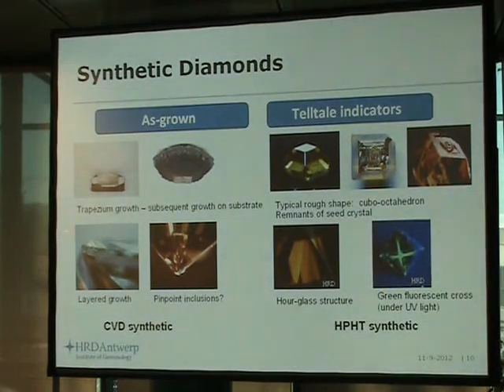Other indications that can point to CVD synthetic growth is that you could have some layered structure indications or pinpoints, but these only are indications. For conclusions, you have to go further. With respect to high pressure, high temperature synthetic diamonds, one can encounter remnants of the seed crystal, metallic inclusions, because the high pressure, high temperature synthesis method includes metal catalysts to facilitate the growth. Other indications can be hourglass structures or, under UV, typical green crosses. And these are all reflections of how these diamonds grow.